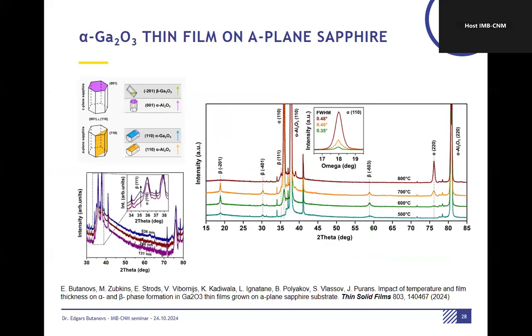Another thing I already mentioned that we studied from the sputtering perspective is alpha phase thin films. M plane is a bit well known to use, but we can also use A plane sapphire. Typically, people use C plane sapphire, so it's this 001 cut, which is the most common. If you take a look here, this -201 famous beta gallium oxide orientation aligns very well with this C plane orientation. But if we take a sapphire with other planes, usually M or A, we have a very nice epitaxial match with alpha phase gallium oxide.